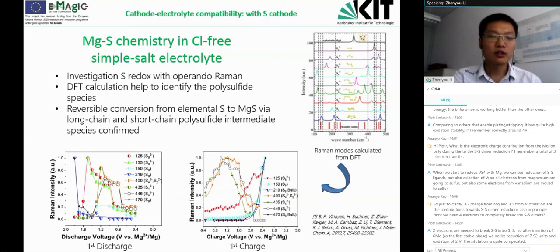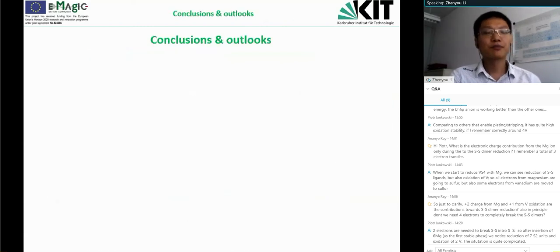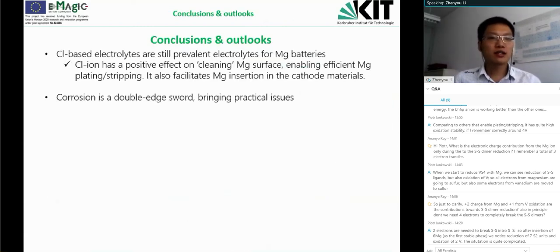And so this reaction mechanism is quite similar to what we have investigated before using the chlorine-based electrolyte. So this also means that our electrolyte is compatible with the sulfur cathode. To sum up, I would say that the chlorine-based electrolytes are still the prevalent electrolytes for magnesium batteries.